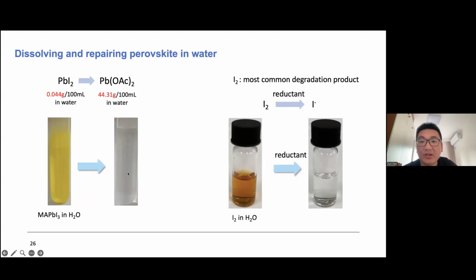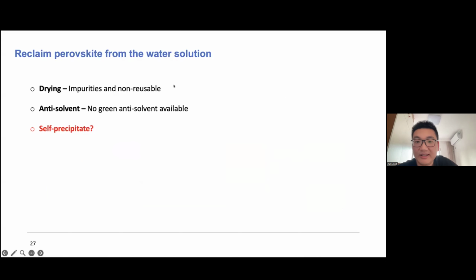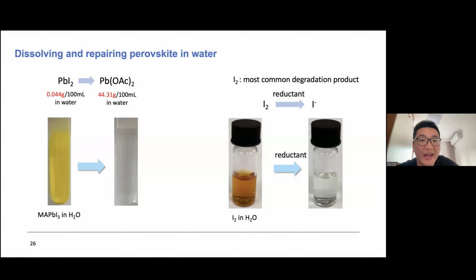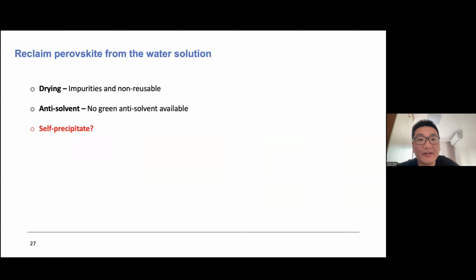And then another thing that we are trying to solve is that we are treating the degraded perovskite, not the common perovskite. So we need to fix the degraded perovskite. First, I2 is the most common degradation product in perovskite solar panels. So we introduce the reductant into the solution to reduce the I2 to iodide ions. And then we try to combine them all into the perovskite recycling. So it's not just dissolving, right? We have to dissolve and repair, but the final thing is how we can get the perovskite back from the water solution.